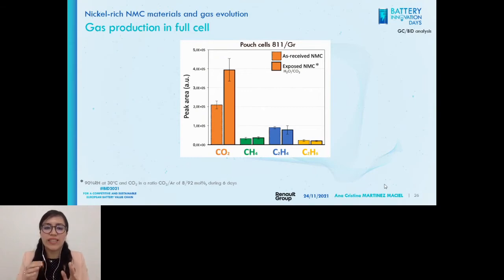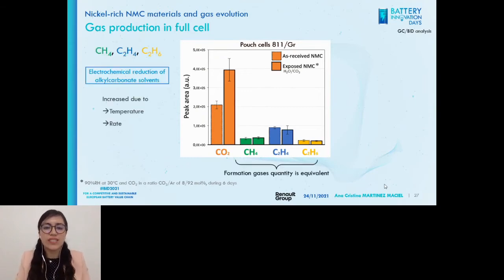You can see that the three formation gases, CH4, C2H4, and C2H6, are almost constant regardless of the surface state of NMC. This is normal because, in fact, they are produced from the first charge of the battery, so they are not really related to NMC at this stage. Later I will show you something very interesting about them. They are just increased by temperature and by rate.